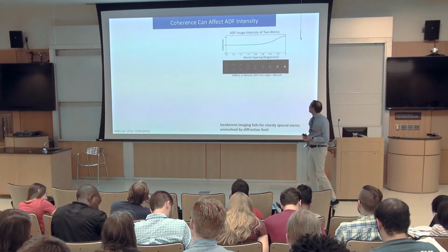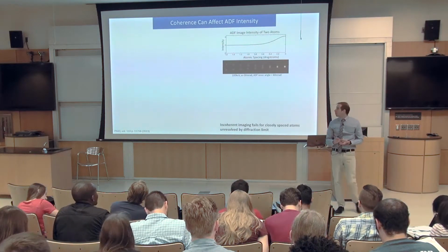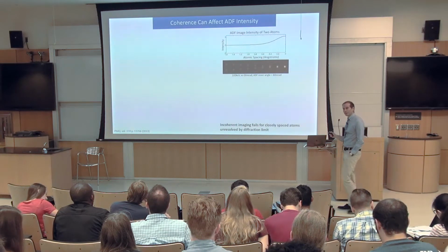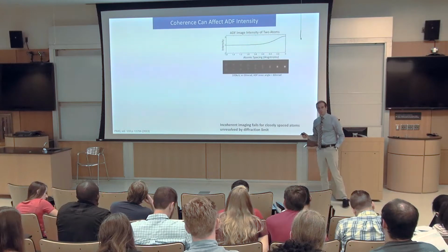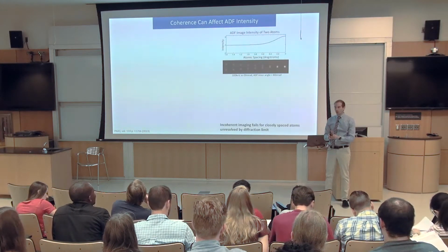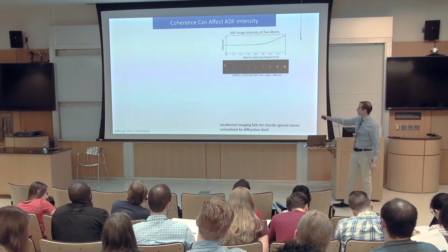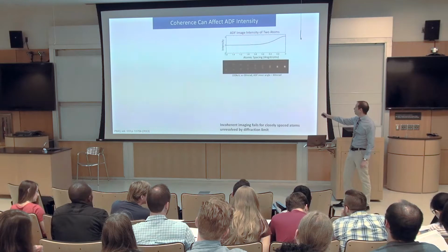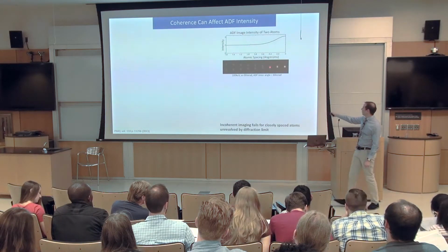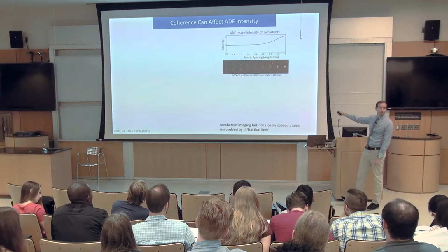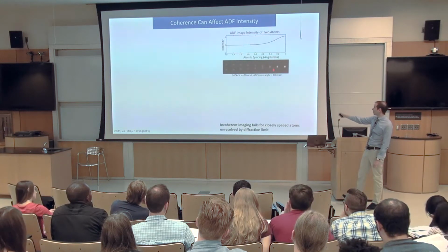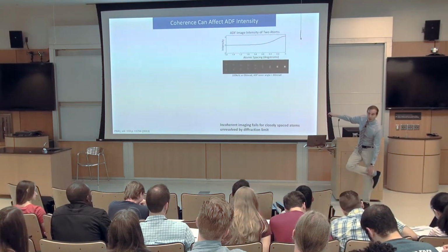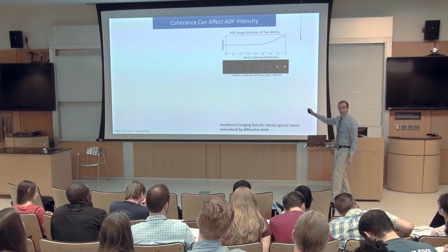So we said that the intensity depends on Z number in an incoherent imaging system. However, there still are coherence effects that can creep into annular dark field STEM, in particular when atoms get really close to each other. So if we look at the total intensity of two well-separated atoms, we normalize that intensity to be a value of 2. As we bring the atoms closer and closer, eventually, once we're past the resolvable limit, so the atoms are now unresolved, there becomes a point at which the intensity increases. And when the atoms are on top of each other, the total intensity increases to 4.